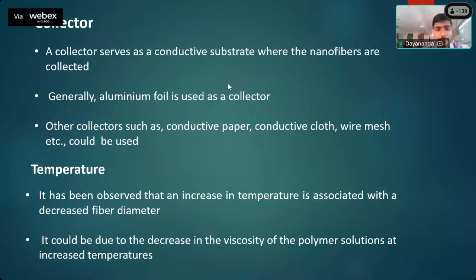The last parameter is temperature, which is very important. When using high boiling point solvents, sometimes we may need to use a little higher temperature; otherwise the solvent will not be evaporated completely. Increasing the temperature could reduce the viscosity of the polymer solution, which finally influences the morphology of the nanofiber mat.